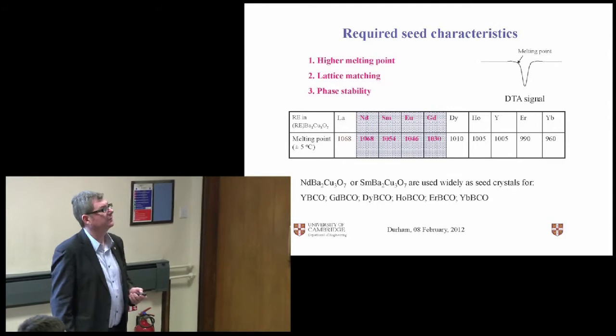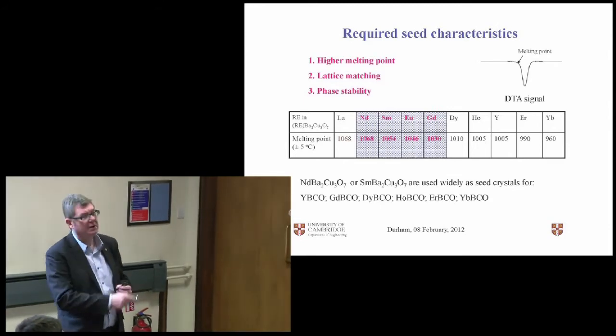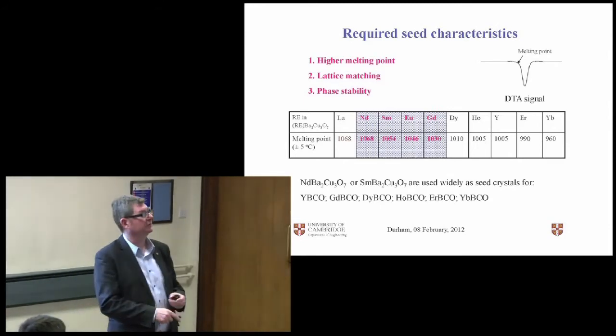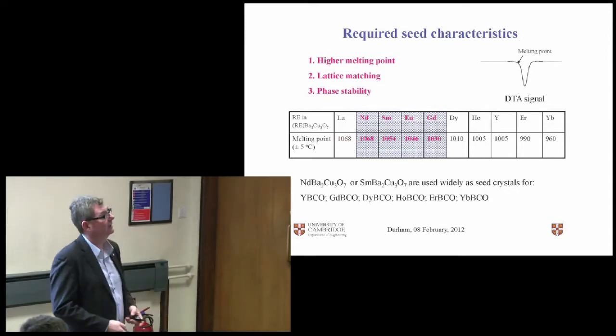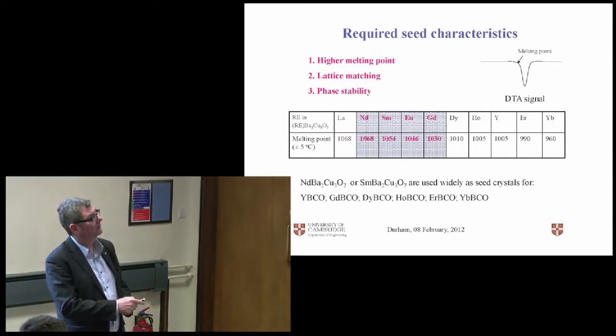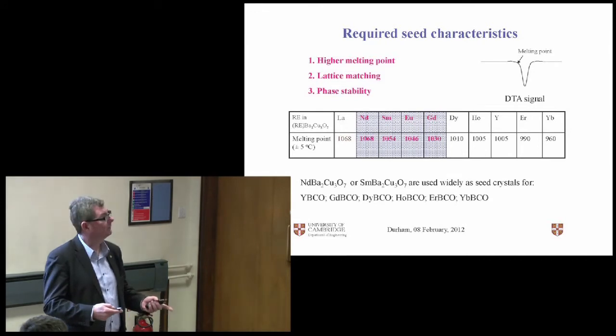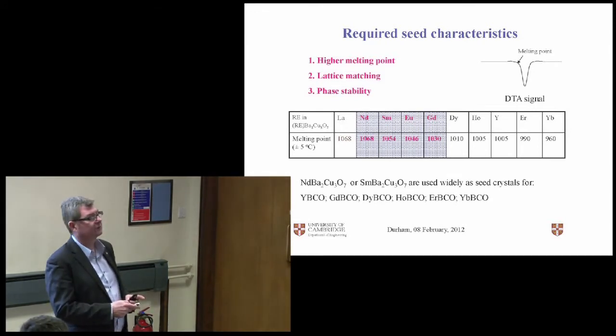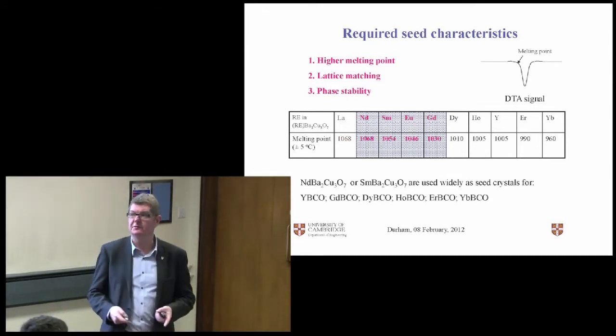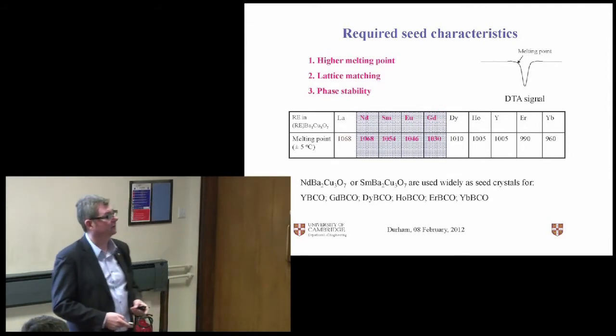So what do we need from the seed? Well, obviously it's got to have a high melting temperature, because if it doesn't, it's going to melt before our parent sample does. It's got to have a good lattice match, so we get a good crystallographic phase. And it's got to be stable. There's no point if the seed reacts with the material we're trying to grow.